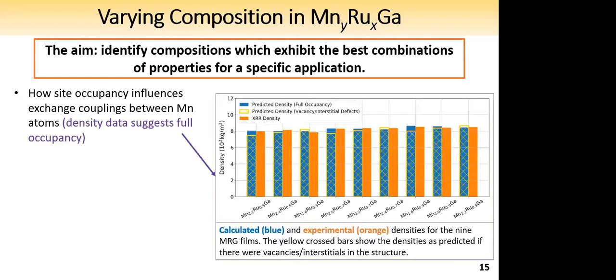And so first, I want to show you this bar chart, this histogram of the densities. It is very important that when we vary manganese and ruthenium contents, we wanted to see if we have vacancies or if we have full occupancy. And in order to do that, I deduced the density of the films using XRR. So I was able to fit the XRR pattern and then derive the density. And that's given by the orange bars.